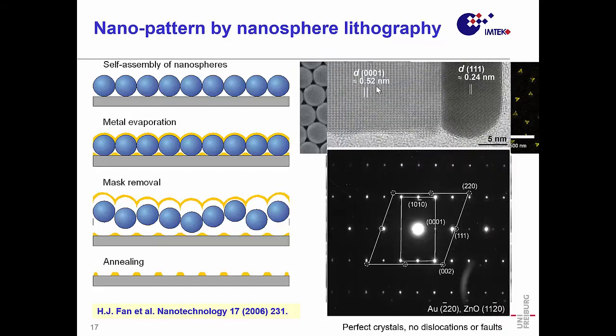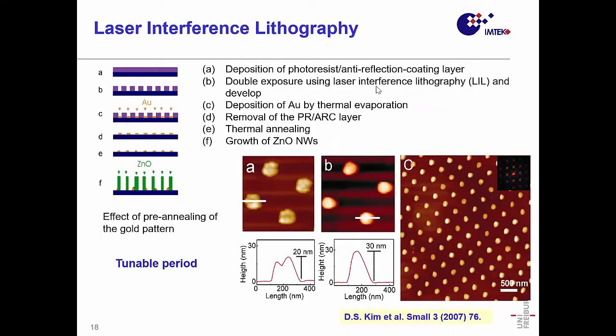Okay, so the nanowires, that's one of the advantages why people are so fascinated by this nanowire growth. They are single crystalline, and very often, not in all cases, completely defect-free. And you see it here, the lattice is completely without stacking faults. It's really beautiful, and that means you are expecting very good properties for that. So that is one method.